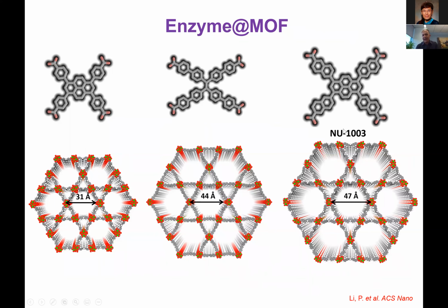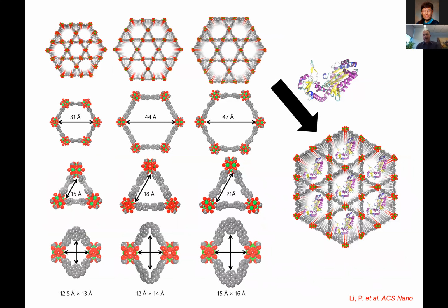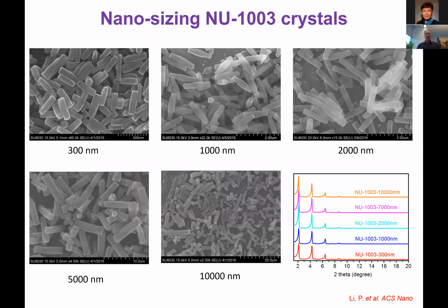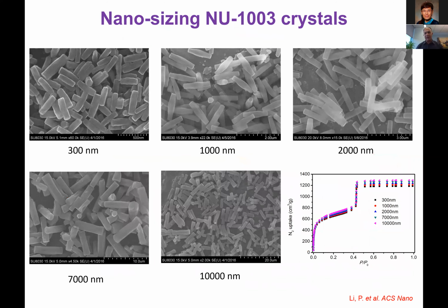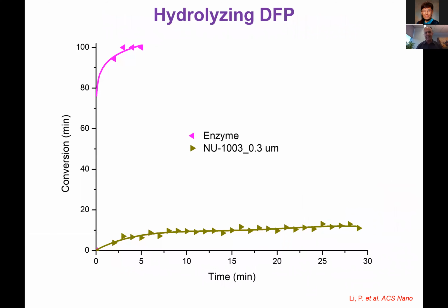It's called NU1003. We do the encapsulation of this material the same way. And now we are able to make crystallites all the way from 300 nanometer to about 10 microns. You could see here the PXRD, everything looks the same regardless what the particle size. More importantly, the nitrogen look the same. That means we are making the same material, except we are modulating the particle size. Now the question, how does it work?